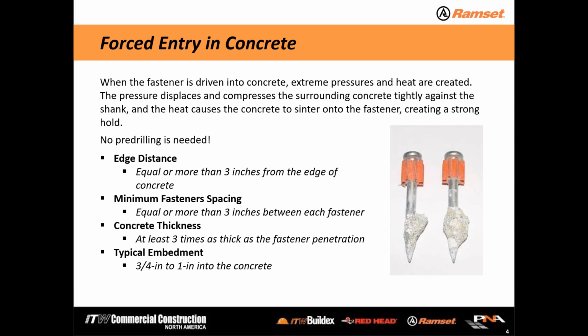Couple important things here. Edge distance. When we talk about shooting fasteners into concrete, with concrete being fairly brittle, you need to stay away from the edge about 3 inches. And you'll find that there's kind of a rule of 3 going on here. 3 inches away from the edge of the concrete, with all that pressure of the fastener making its own hole and going in,